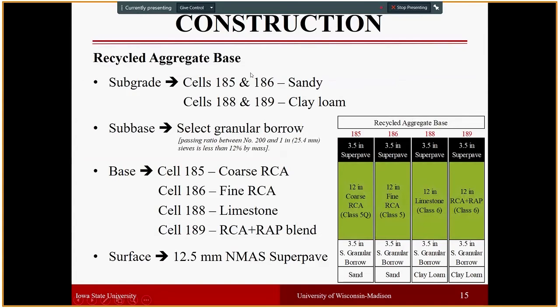So for the recycled aggregate bases, these are cells 185, 186, 188, and 189. Cell 185 is the test section that has a base built with coarse recycled concrete materials, and cell 186 has the base layer built with fine recycled concrete aggregate. Cell 188 is built with conventional class 6 aggregates as control material, and cell 189 is a combination of RCA and RAP placed as a base layer. One main difference between the recycled aggregate base test sections and the other test sections is that we have sandy granular borrow material as a subbase, and cells 185 and 186 have sand subgrade, while 188 and 189 had clay loam subgrades.